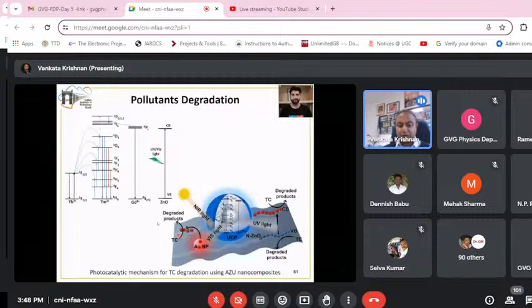Then we did a detailed analysis of the mechanism based on experimental findings as well as literature reports, which indicates that when NIR light falls onto this material, it emits both visible light and UV light. The visible light gets absorbed by the gold nanoparticle, leading to surface plasmon resonance, which leads to degradation of the pollutant.